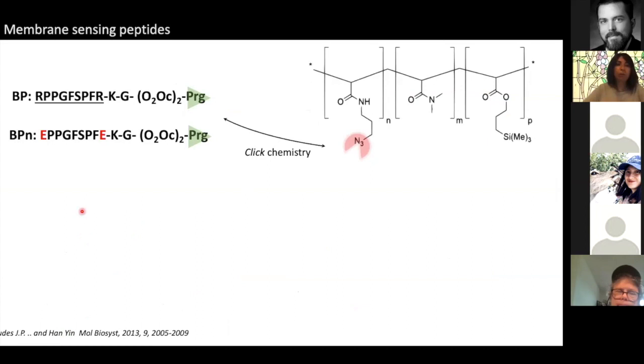So starting from this sequence, we have designed molecules, probes, engineered peptides, starting from this 9 amino acid sequence that is reported here. We call it bradykinin-derived peptide, BP, and we also designed a mutated peptide in which the arginine residues were mutated to glutamic acid to revert the electrostatic charge of the peptide from positive to negative. And this is our negative control. And as you can see, both probes bear a spacer, a short PEG linker, and a propargyl glycine, which is a non-natural amino acid that we use to bind the peptide